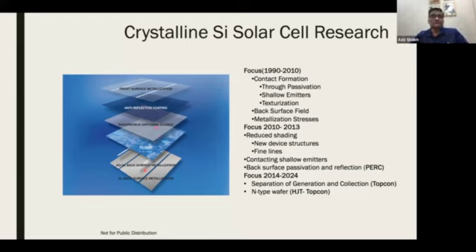Okay, so if you want to improve the efficiency, from 1990 to 2010, this is the era when the US was gradually improving the efficiency. So it was to reduce the resistive losses through better contact, through passivation of the surfaces, back and the front, making emitters shallow, and texturization to reduce the reflection. On the backside, forming the P plus charged layer so that the carriers are reflected back. So these are the techniques where the focus was.